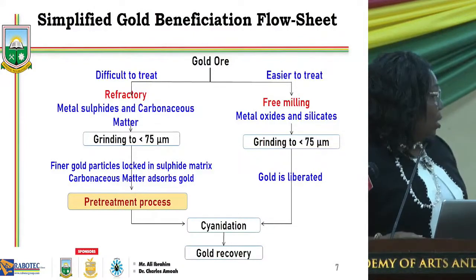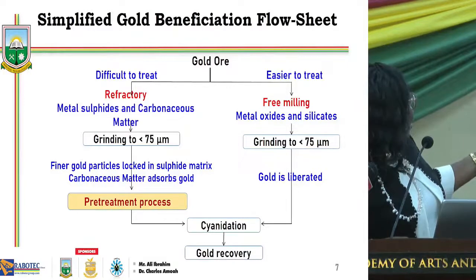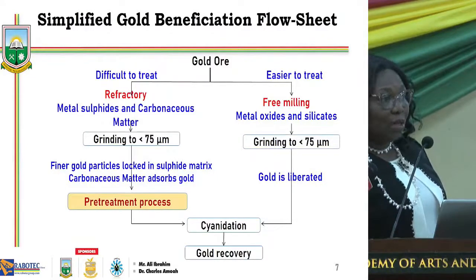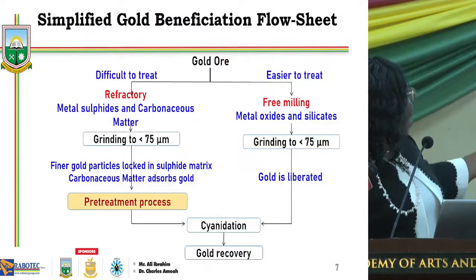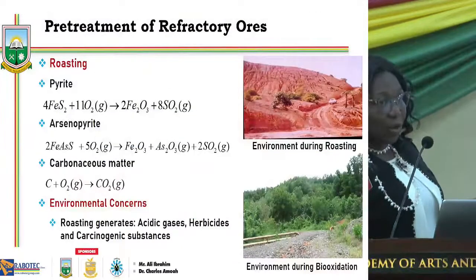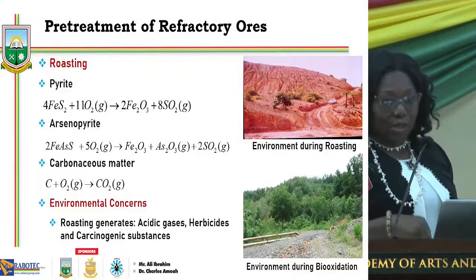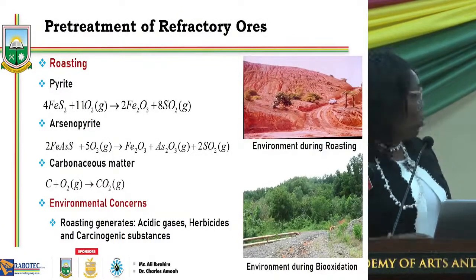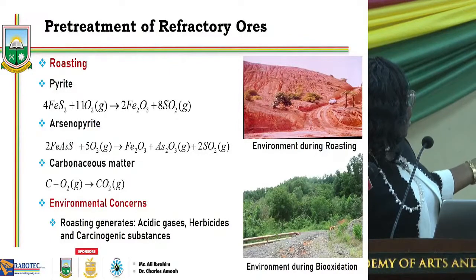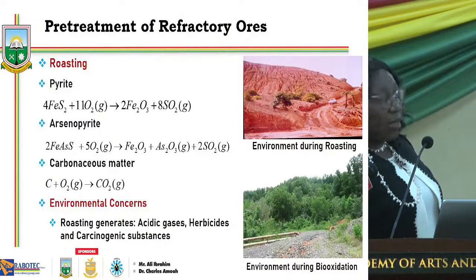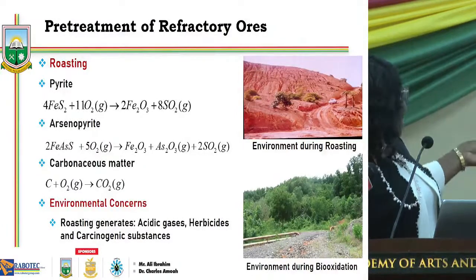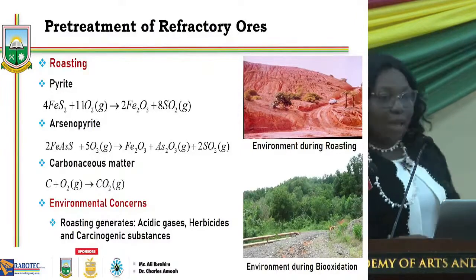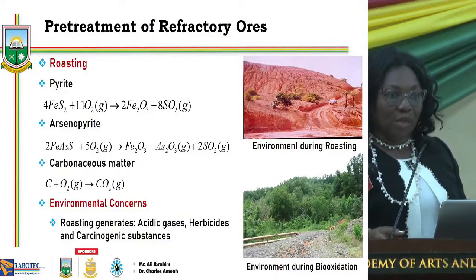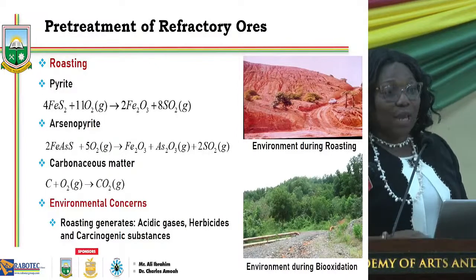So if you look at these equations, we have pyrite here, sulfide, oxygen, and then we produce oxide and a gas. Arsenopyrite is also a sulfide. When we heat it, we will produce an oxide. This is hematite, iron oxide, which will contain the gold in the solid state. But it is porous, so the gold can be dissolved. And we are going to form gases. When we have carbonaceous matter, we heat it, we are going to produce carbon dioxide. So these gases are acidic. They can act as herbicides and chop off weeds. And they can also cause cancer.